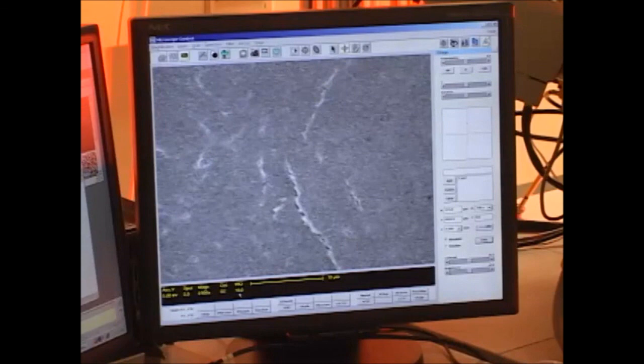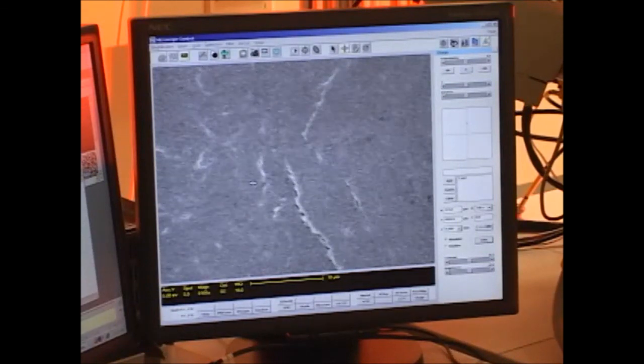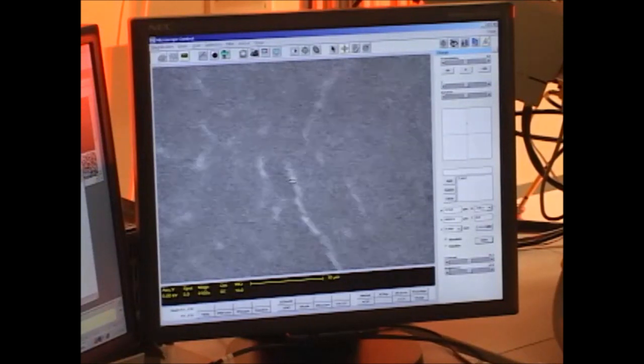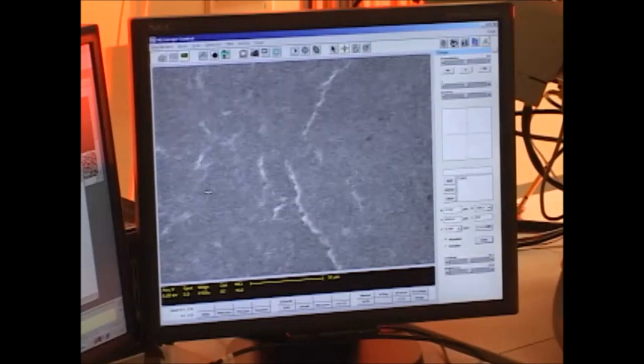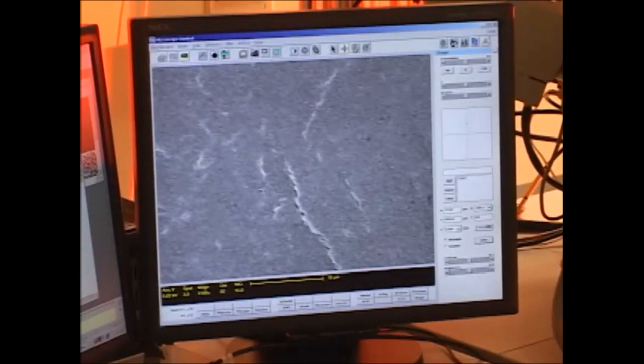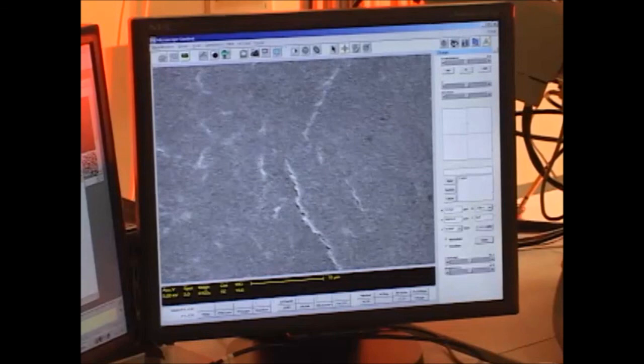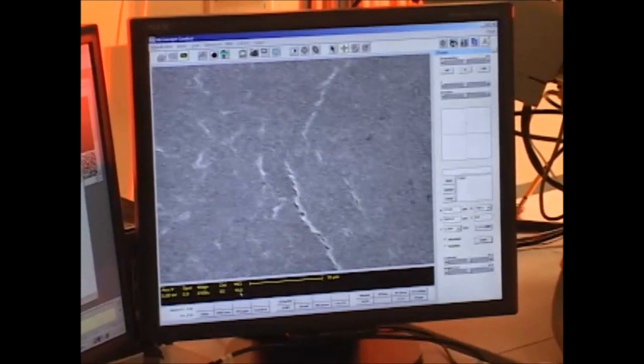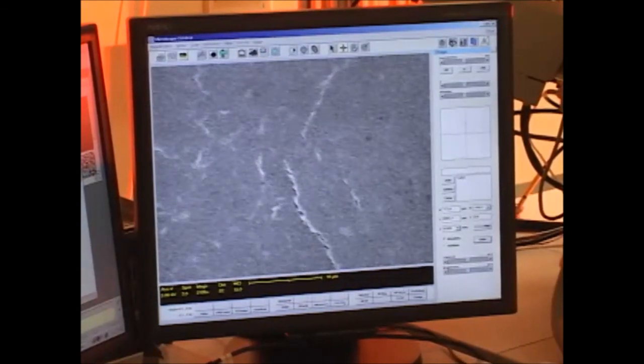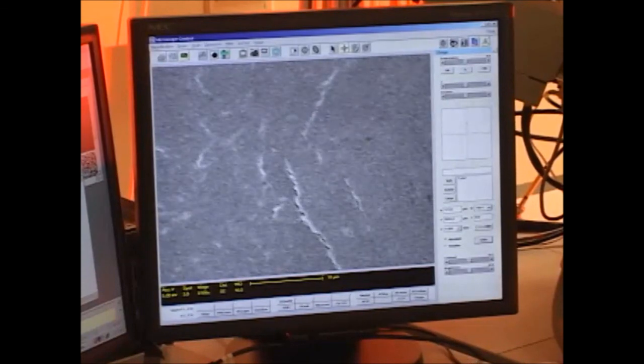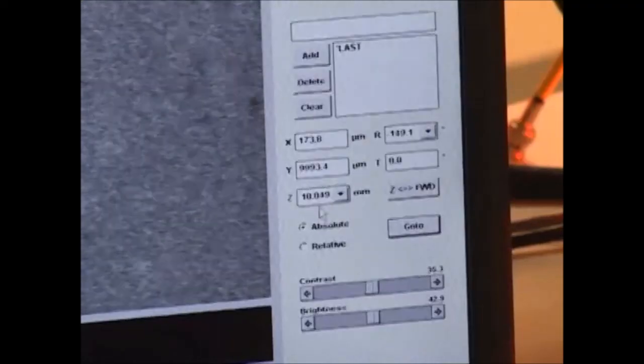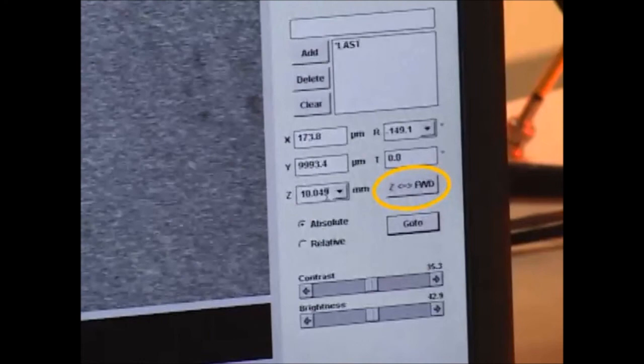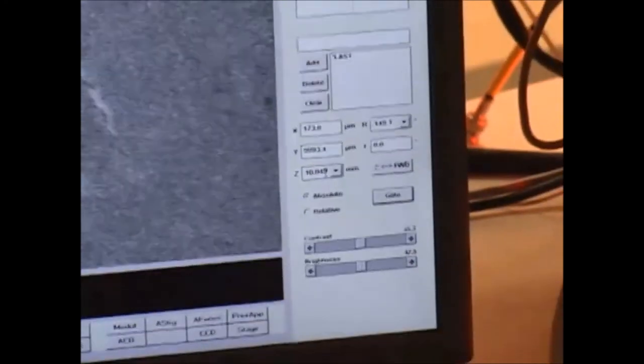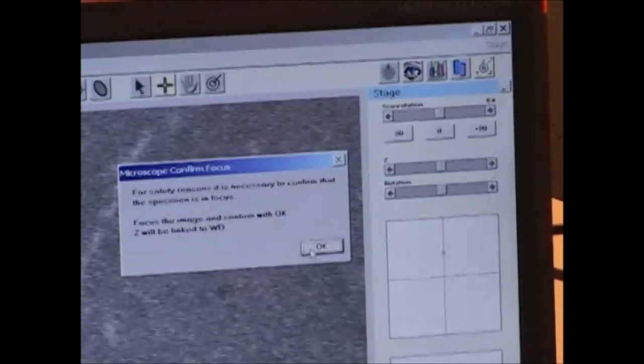And after I've told it to move to 10 millimeters, I need to refocus and actually tell how high it went, because it'll be slightly off from 10. I'm going to focus again to get the best possible focus. I can see that I'm off by less than 1/10 of a millimeter in this case. But I want to recalibrate the height of the stage. To get the dialog box back, I click on Z, forward working distance. And again, I want to confirm that the sample is in focus at more than 2000x by clicking OK.